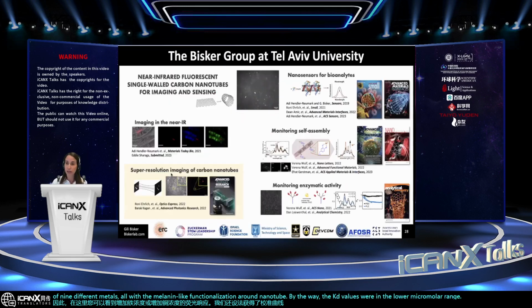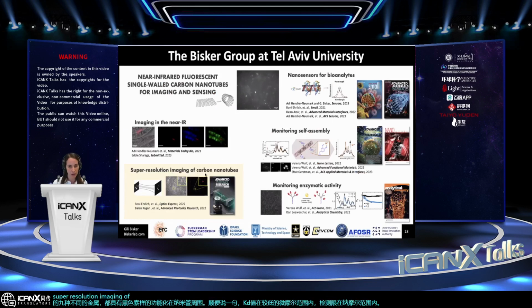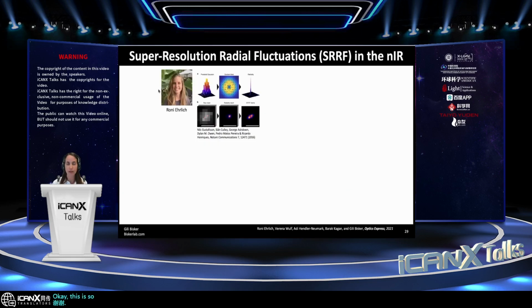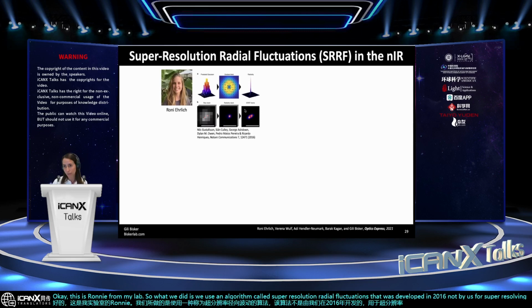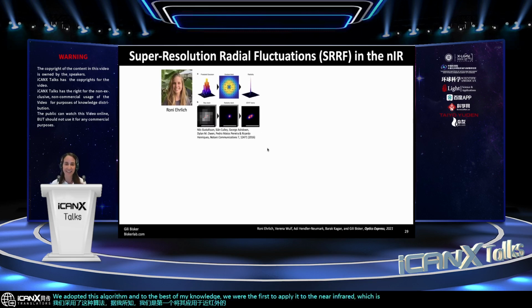Super resolution imaging of single carbon nanotubes. Okay, this is Ronnie from my lab. So what we did is we used an algorithm called super resolution radial fluctuations that was developed in 2016, not by us, for super resolving visible fluorescence images. We adopted this algorithm, and to the best of my knowledge, we were the first to apply it to the near infrared, which is where the challenge is more difficult because of the longer wavelength.